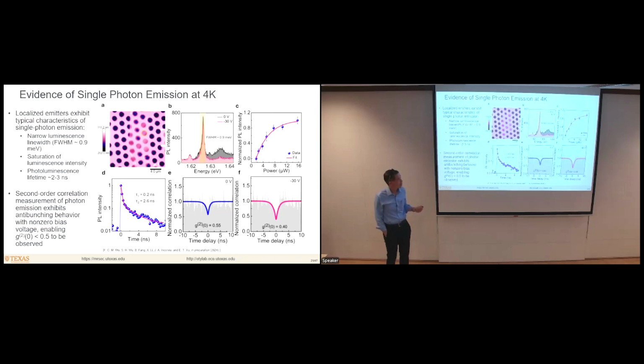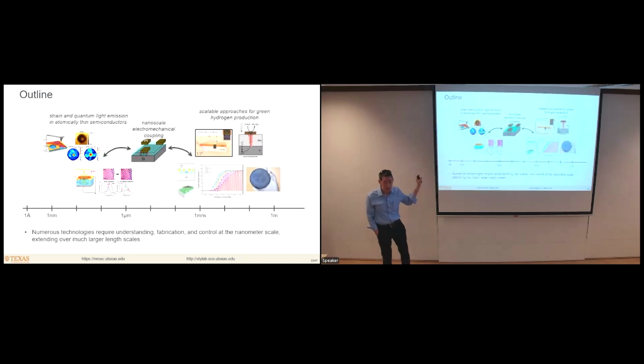So what this series of results shows is that it is possible to dynamically modulate strain in these structures in a way that also modulates the luminescence properties, and in particular, here, the observation of what's generally considered to be the proof of single photon emission. And it opens the door to doing more detailed studies of how strain influences luminescence and single photon emission, and perhaps using an approach like this to modulate the behavior of single photon emission. So that's basically what I wanted to say about the TMD materials.